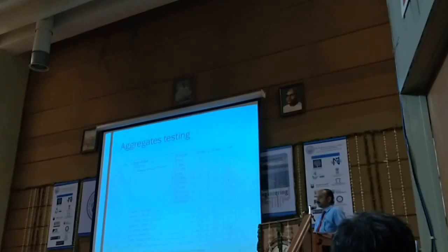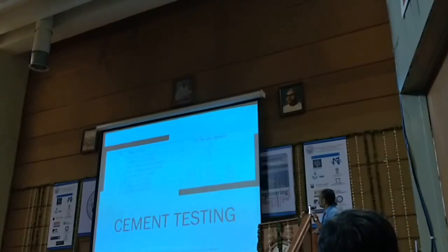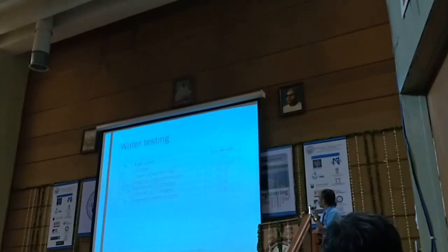As far as the material tests are concerned, following the IS 383 guidelines and other guidelines, these aggregate values were obtained: the gradation, fineness, impact value, crushing strength, flakiness, elongation indexes, specific gravity, water absorption, and silt content, which were mostly conforming to the provisions of the IS code. Similarly, we had the tests for cement regarding its fineness, standard consistency, IST, FST, and compressive strength. The water that was to be used, as this test was getting performed in the region of Valsad, was mostly of good quality for construction. It is not containing any salts.